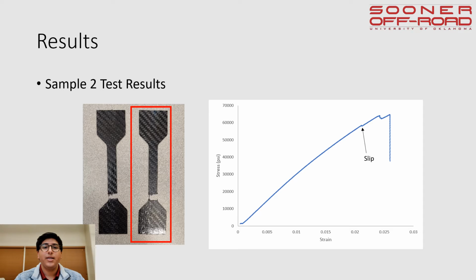In the second sample tested, the yield strength was determined to be 64,000 psi, and 64,700 psi for the ultimate tensile strength. Changes in the values were determined to be due to a small slip in the jaws that might have altered the data. There were 5 samples tested, and of those, these 2 were the best, which had the smallest amount of slip. Regardless of that small slip, the carbon fiber samples were greater in strength than the 4130 steel that they would be bonded to later in the research.